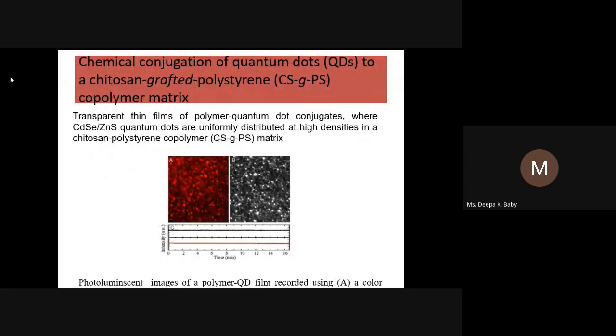Then in the same matrix, you can attach quantum dots. The quantum dots cannot be attached to every polymer matrix. Some specifications could be needed. So I have docked cadmium selenide ZnS quantum dots into this chitosan graft polystyrene matrix. This is the image of the quantum dots, and if quantum dots are incorporated in the polystyrene chitosan matrix, then it can be used for targeted drug development. So these are the applications of chitosan for drug delivery, and with this slide I am coming to the end of the session.